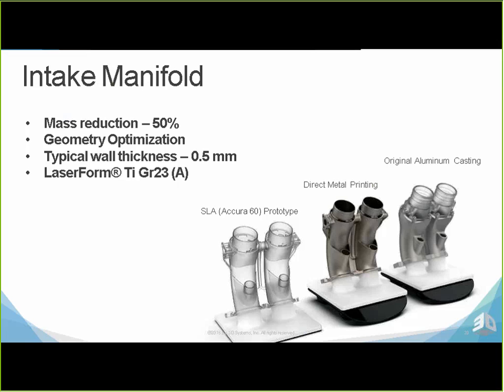So here's another automotive application, and this one really hits on every subject of lightweighting and optimization. Generally, an intake manifold would be an aluminum casting, and as you're building through castings, you've got complex gating, minimum wall thicknesses, a lot of material that really is for the casting process, not for the final result. So the original aluminum casting is really going to be limited, and you cannot add lattice structures or really go to super thin walls. But what you find is if you really are trying to optimize a structure like an intake manifold, one, aluminum is not the best metal for it. Really, titanium offers you a better strength to weight ratio. And two, the optimized structure for this, it's not necessary to have thick cast walls. It's only necessary because of the casting operation.